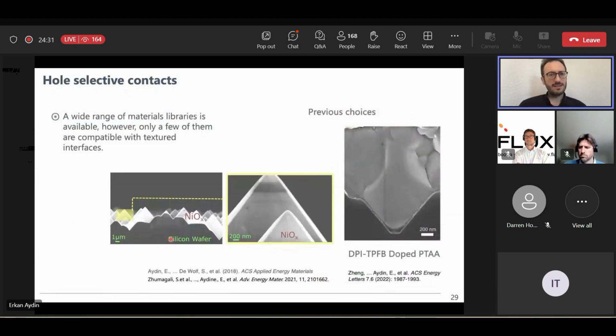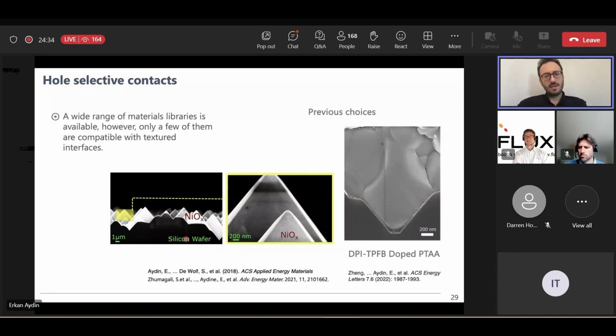But for sure, we didn't stop there, and we continued looking at the other contacts, and this time the hole selective contact. In 2020, when we first introduced this double-side textured tandem with solution processing, we were using nickel oxide. Then later on, we passivated nickel oxide because we found that there are redox reactions happening at the nickel oxide perovskite interface. But still we had voltage losses, and then we also tried to adopt one of the best polymeric hole transport layers in the literature. It's PTAA, and we tried to dope it, but we never reached a level of conformal coverage with this method, although the sputtering was quite nice.